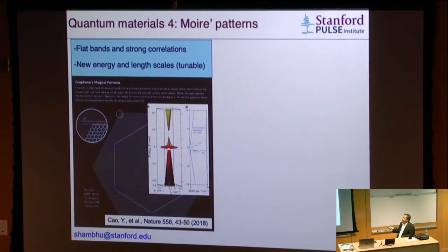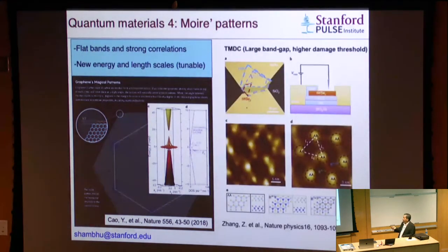Not only that, the band structure has something really interesting, what's called the density of states. They get peaked up, and the material even becomes superconducting, and all that exciting stuff that is going on in the community. And you might know the work from Leroy group here at the physics department that this can be realized in TMDCs. I like TMDCs more because they have a certain band gap and they have a high damage threshold for the laser. So the experiment, as they have shown the Moiré pattern on this material, it would be really nice to probe the Moiré lattice with high harmonic spectroscopy.